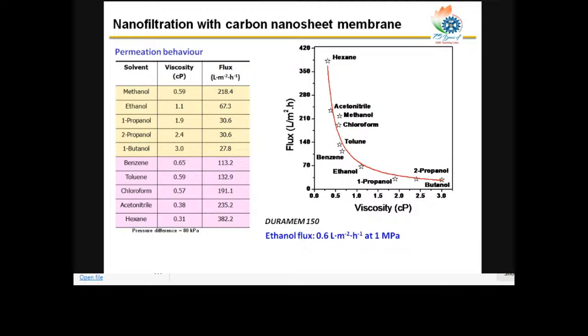Now, the interesting part about this one, these nanofilm membranes, they are porous. We can pass some solvent through it. We can reject some molecules using this membrane. But the most interesting part is this graph. If you see the flux versus viscosity, depending on Poiseuille's equation, flux is inversely proportional to the viscosity of a solvent. So I think it's very interesting here that isopropanol, propanol or butanol, which have higher viscosity, are showing very little flux compared to hexane, which is actually giving the highest flux here. So from this phenomenon,